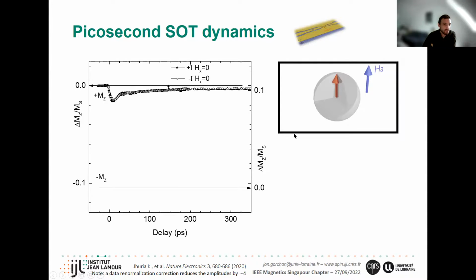And so there are two things going on here. First, we're heating up the magnet with an ultra-fast impulse. And so this looks very similar to the optically induced ultra-fast demagnetization. So you just quench the magnetization. And you see a drop in magnetization and it recovers slowly as the heat leaves the ferromagnet. So ultra-fast demagnetization with a picosecond current pulse had already been observed, so it's not really surprising. Now there's a second element here, which is that we are also injecting spin due to the spin Hall effect.